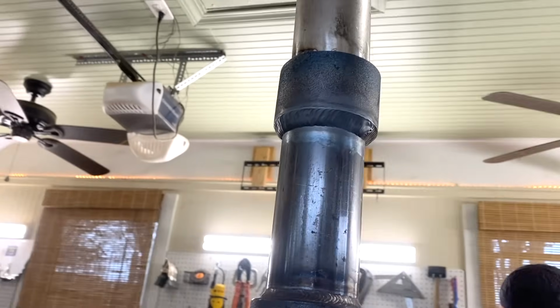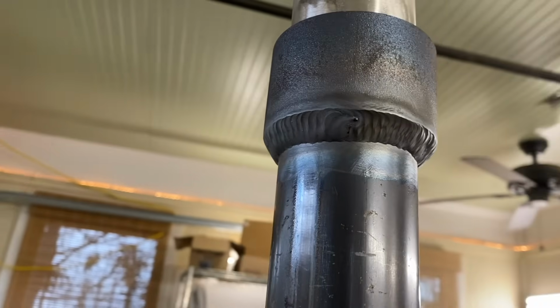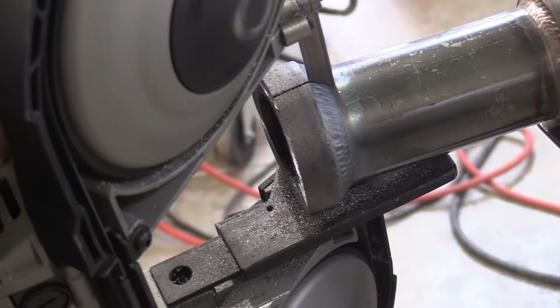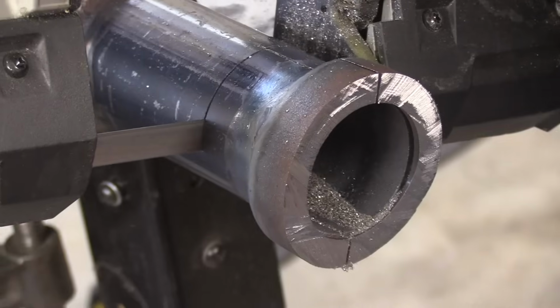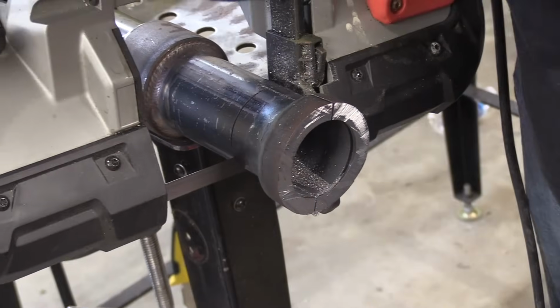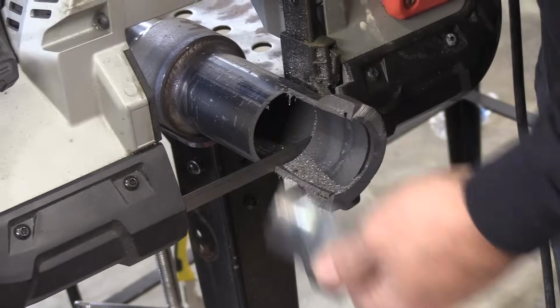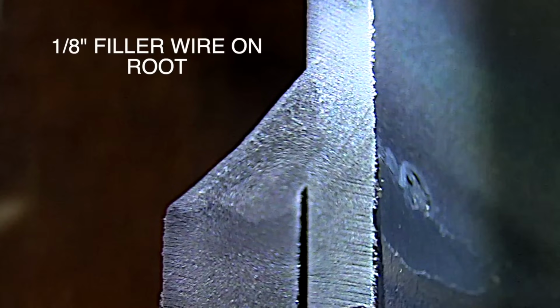We sort of pretended this weld was in a corner, so Andrew welded half of it with right hand, half of it with left. We cut it, sliced it, diced it, polished, etched it, and did a test to verify penetration. You can think you're penetrating, but there's nothing like a test to verify it.